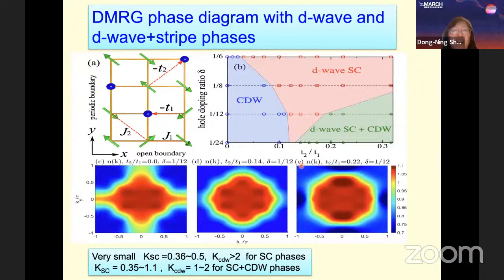Let me go back to have a summary about the 3 quantum phases we obtained. If we fix the filling doping level, then we have CDW, then D-wave with uniform density, and then a superconducting CDW coexisting phase. The transition is induced by increasing T2 over T1.